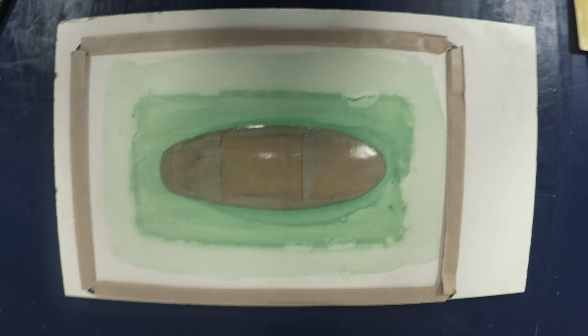Once your mold has the desired surface conditions, you will need to apply a release agent. There are many different products that can accomplish this. On our more complex molds that are made out of more chemically resistant materials, we use products from Chemlease, such as their 41EZ or their PMR release agent. On some mold surfaces, a sealant must first be used to close out any porosity in the material before applying the release agents. As you can see by the green appearance in this mold, the release agent used in this case was various coats of PVA.